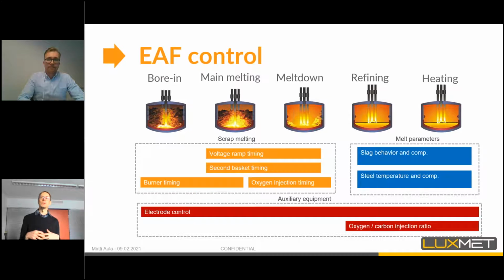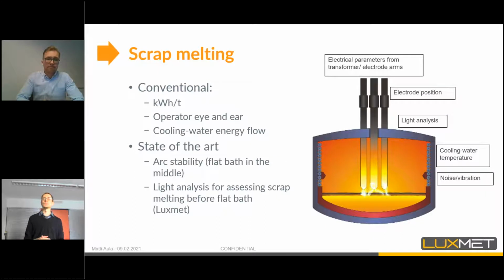And in the end of the process, there is going to be steel and slag formed. At the end of the process, we want to know when is the optimum time to stop the process. First of all, we need the steel to be of the right composition, but it also needs to be of the right temperature. We don't want to overheat the melt or underheat it. Both will lead to serious consequences. As we see from this picture, a lot of these different control variables are related to the scrap melting. So I will be talking a bit more about that.